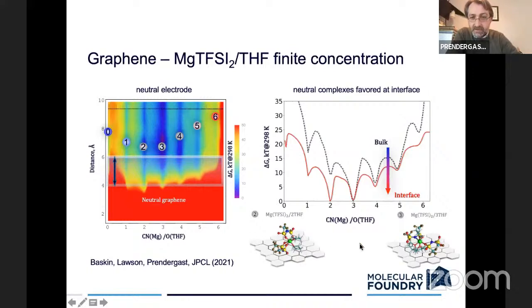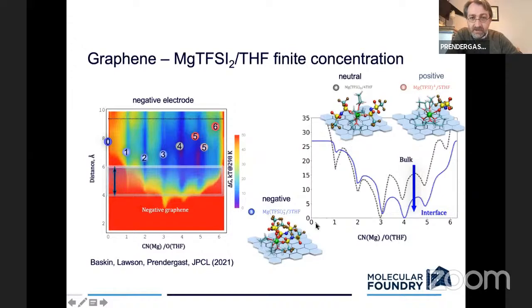I've highlighted the dominant 2 configurations here, which is magnesium with only 2 solvent molecules and connected to 2 different anions. That's at the interface when there's no charge. Now, if we electrify the interface, make it negative, what you find is that there's a shift.